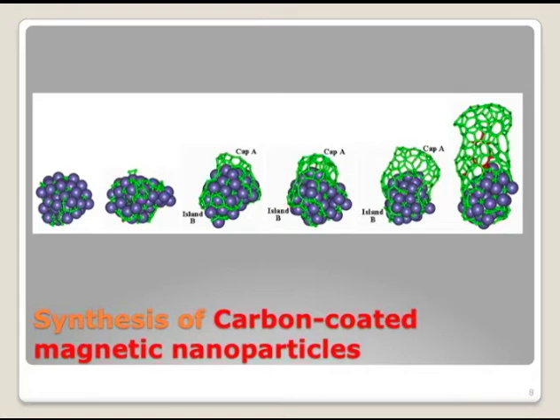If we stop in the middle, before the nanotube grows out, we get carbon-coated nanoparticles. So this is our method to synthesize carbon-coated magnetic nanoparticles. Usually, growing carbon nanotubes takes half an hour to 1 hour, but here we only let the reaction happen for 5 minutes. So after purification, we should get the graphitic shell-coated nanoparticles.